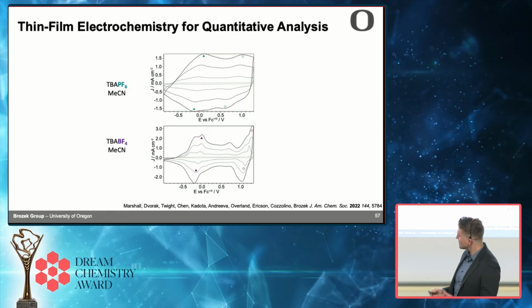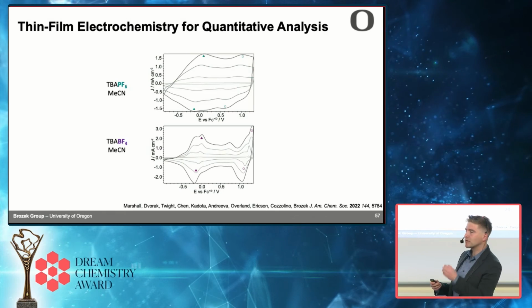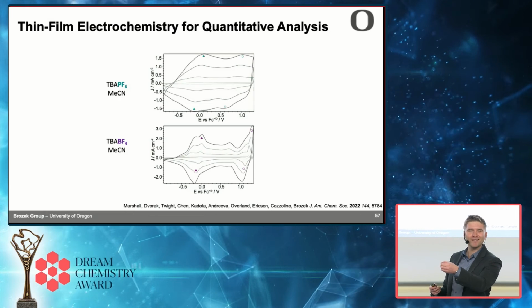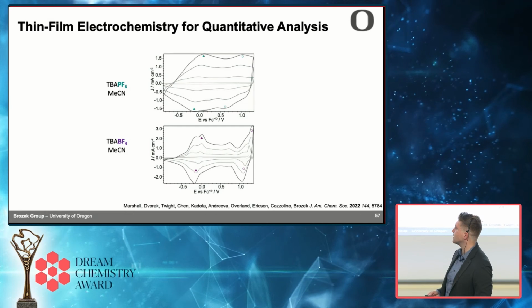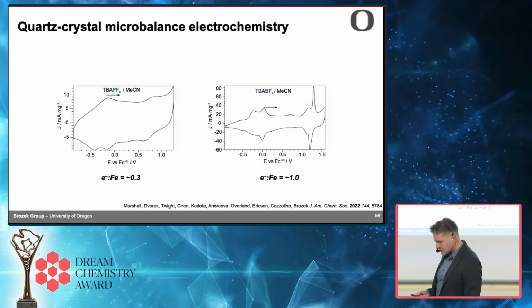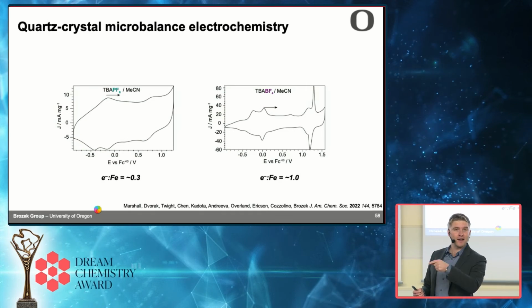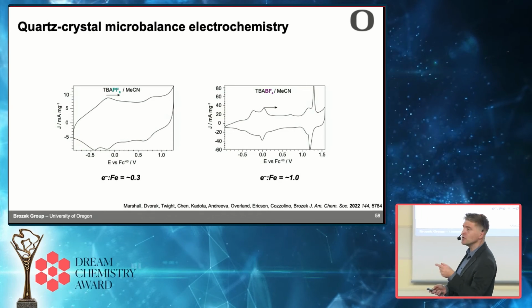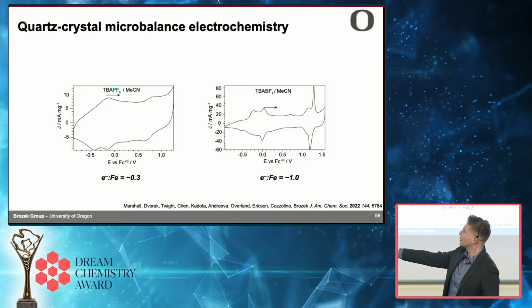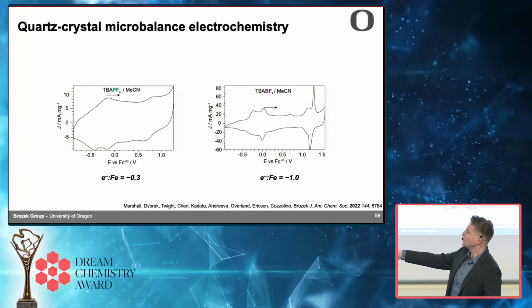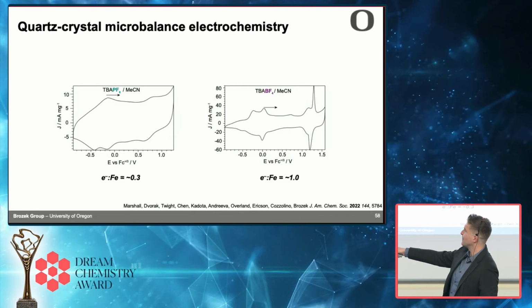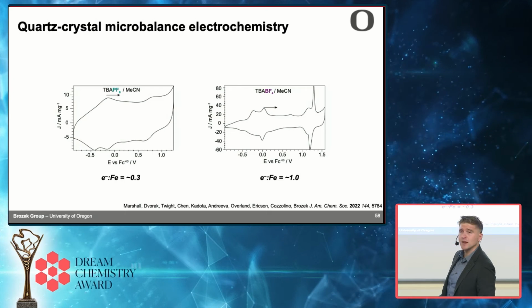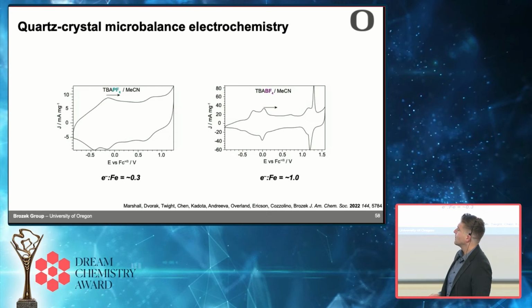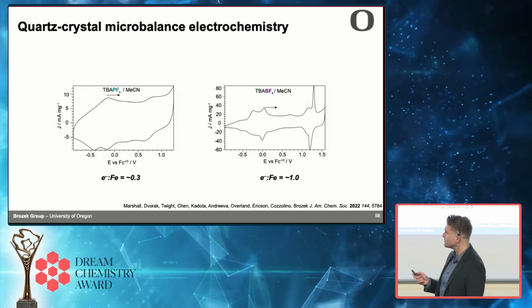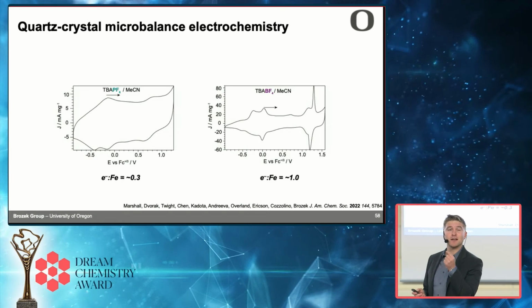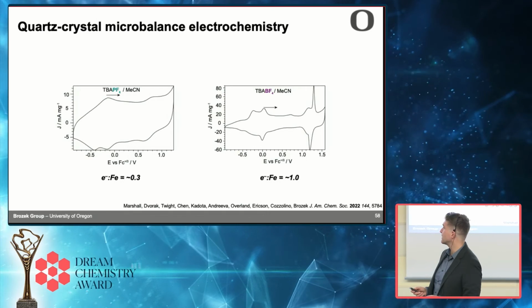And so it started to suggest to us that really the pores are sort of controlling the redox chemistry in this material. And if that's true, you should be able to see the ions intercalate. You could do this using a special electrode called a quartz crystal microbalance electrode. You can use it like a normal electrode. These are the CV traces that you get when you use it like a normal electrode. So it looks similar to before, except what's special about a QCM electrode is you can actually detect the mass of your material during this.